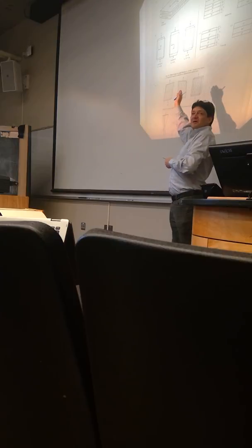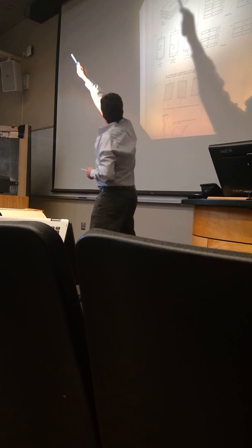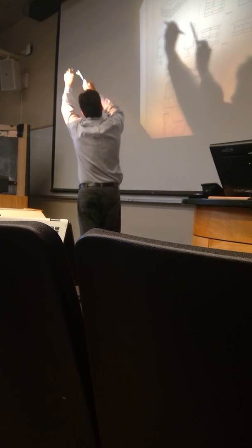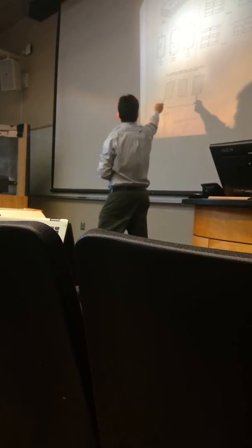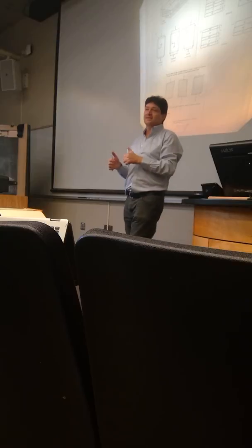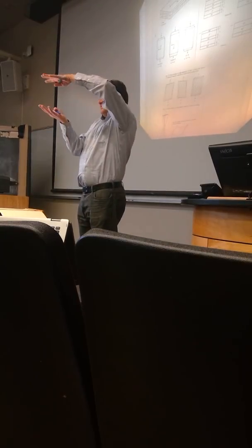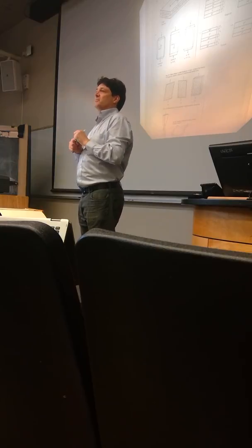It's not what we call a symmetric composite. This upper layer would be stiffer in this direction, and this one's stiffer in this direction, so if you pull on it here, it'll warp and twist like this. So you have to be very careful how you lay up your layers of composite so that you get a balanced and symmetric layup of your fibers so you don't get warping.